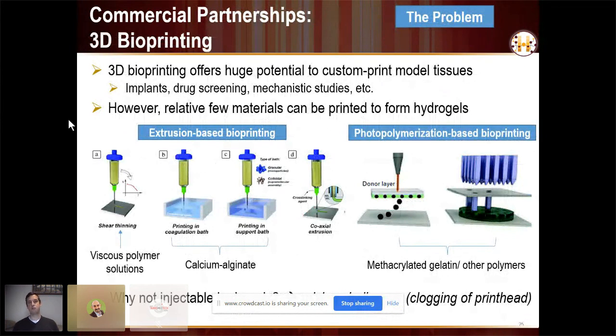So you can either use a shear thinning ink, which you take a hydrogel that shear thins, you can extrude it through the needle and get a hydrogel at the other end, but you're limited in mechanics because you have to still be able to shear thin it enough so that it moves. You can do coagulation bath printing with things like calcium alginate, but then you're really limited in chemistries because almost everything has to have at least calcium and alginate as components of the ink, if not the only component.